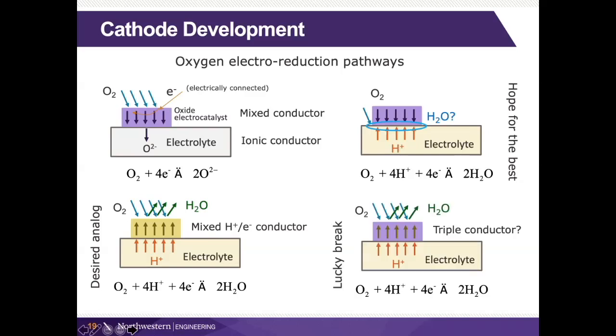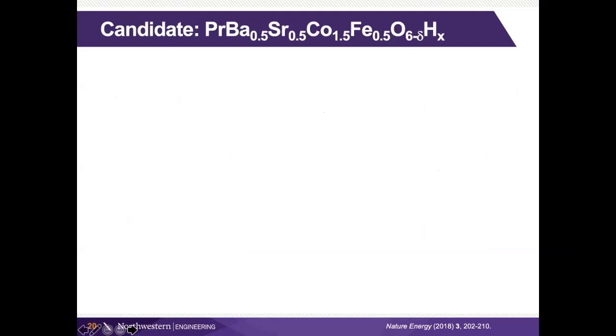And what it turns out is that many of these materials that we viewed as mixed oxygen ion and electron conductors are actually triple conductors, meaning that they in fact do let the protons through. They let water molecules through them as well. So they're kind of squishy for all sorts of ions, the oxygen ions, the protons, the water molecules, the electrons. So everything can go through them. And that's sort of our lucky break, that they in fact work quite well in terms of the transport characteristics. Then we need the catalysis characteristics to be very good as well. And so the material that we've worked with is this large fraction of the periodic table. So we just call it PBSCF.